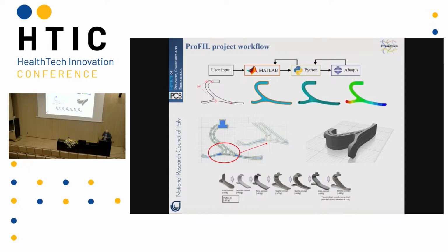In any case, knowing all these limitations, we have developed a continuous system in which you start from your global geometry, then the system is able to have a partial section of this geometry. You have inside the structure with the position of the continuous filament of fiber, and then the simulation of the structure in order to have the results in terms of mechanical resistance. This is a loop. You continue to do that in order to obtain the optimization of your final geometry. This is some evolution of what we were thinking at the beginning of the project. We are doing it now, more or less.